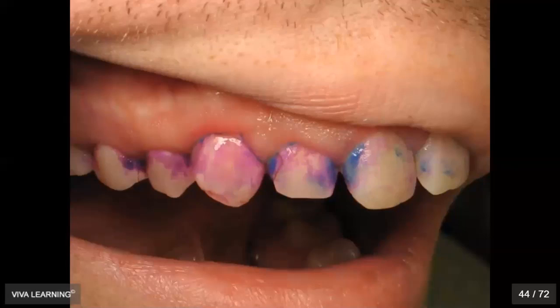When I dye his plaque with Triplaque ID Gel to identify where the acidic plaque is, look at the blue plaque in between his teeth. That is pH 4.5 plaque. That's not going to demineralize just hydroxyapatite. That's going to demineralize fluorapatite. It's pH 4.5. No amount of fluoride can stop that stuff. And when I say no amount of fluoride, I mean fluorapatite, because fluorapatite has a critical pH of 4.5. So I want to do everything I can to keep those restorations saturated with as much fluoride as possible. Drive up the fluoride content to try to neutralize this plaque, or better yet, put something in this patient's mouth which is going to neutralize those plaque acids. It's going to be drawn to the tooth surface, like the casein protein, and slowly release ions that can buffer those plaque acids over time.